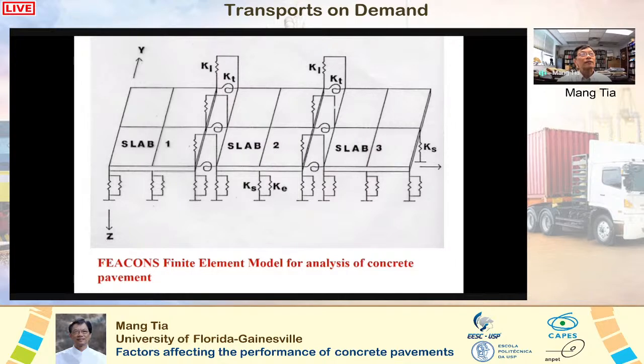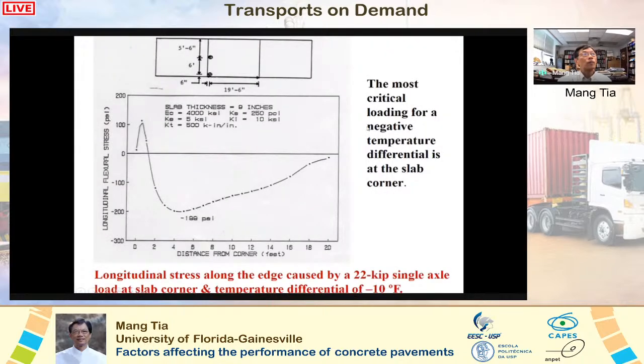To help with our evaluation, we developed a finite element model called FEACONS for analysis of concrete pavement under the combined effects of loads and temperature differentials in the concrete slab. It also had the capability to model the effects of joints and edges, and also model the behavior of concrete slabs, which is either bonded or not bonded to the base layer. So with this finite element model, we are able to do a lot of analysis.